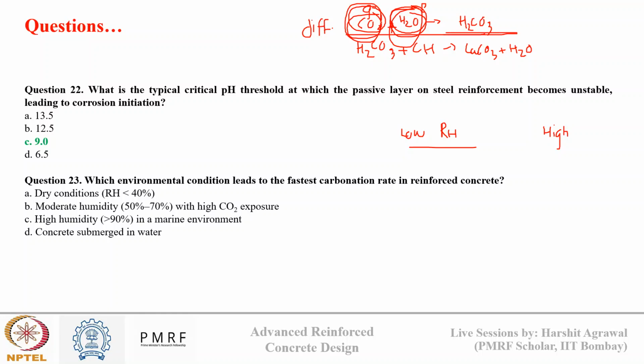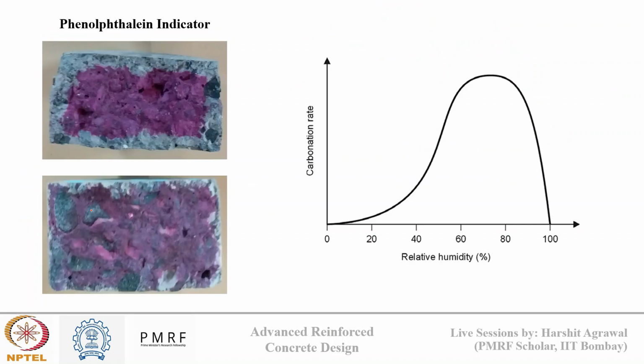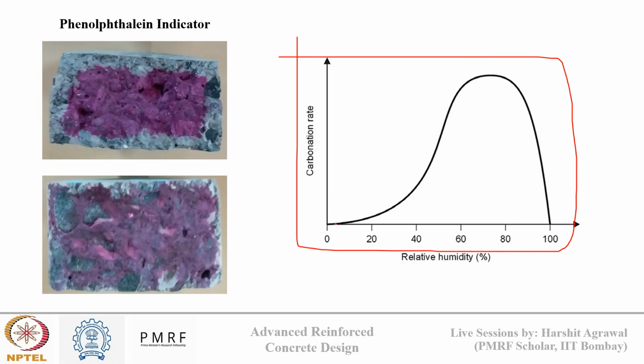So that's why there will be less amount of CO2 in the concrete, and then again this reaction will be slower. So that's why we need a moderate humidity to accelerate the carbonation the fastest. And this you can see here, the carbonation rate versus relative humidity graph. At lower relative humidity, carbonation rate is small. At high relative humidity, it is small, but in this range of 50 to 70 or 60 to 80, it is maximum. There is enough water in the system for carbonic acid to form, and there are enough air voids in the system for CO2 to penetrate.